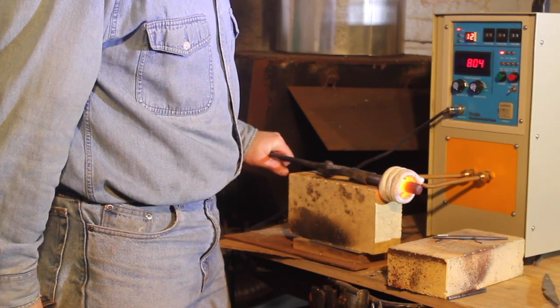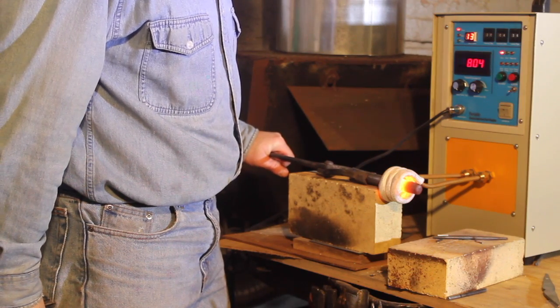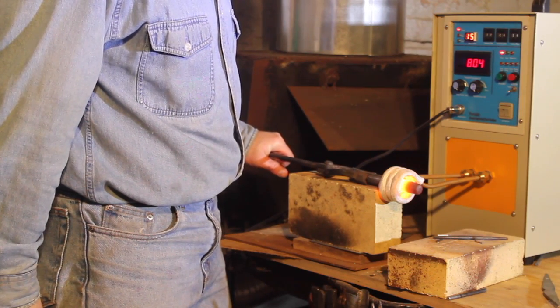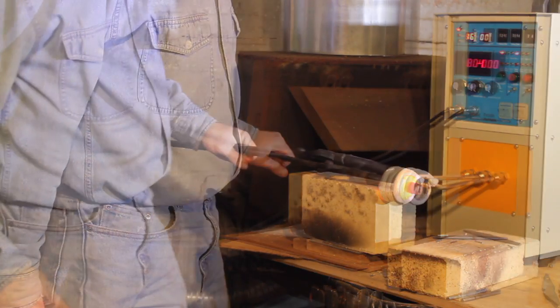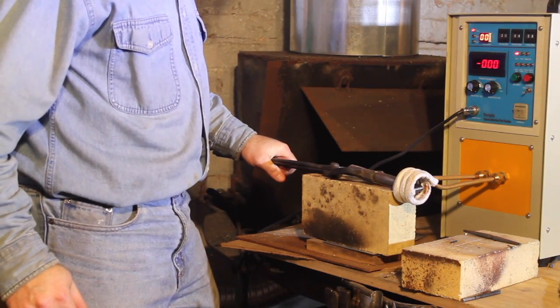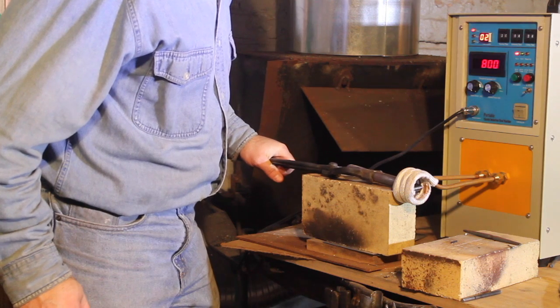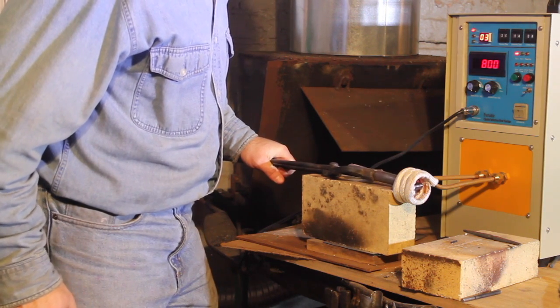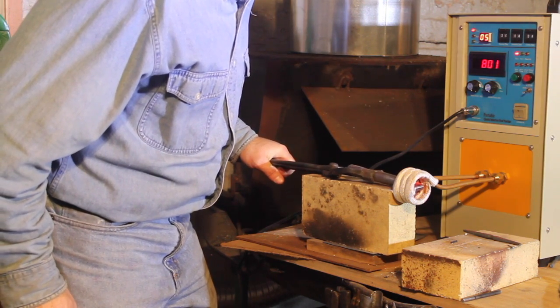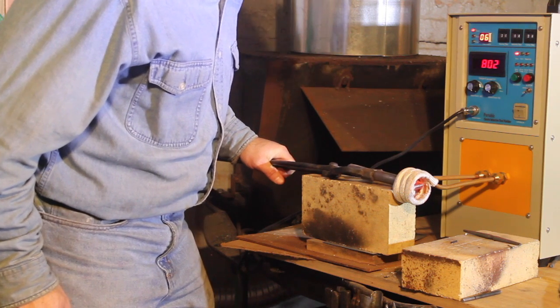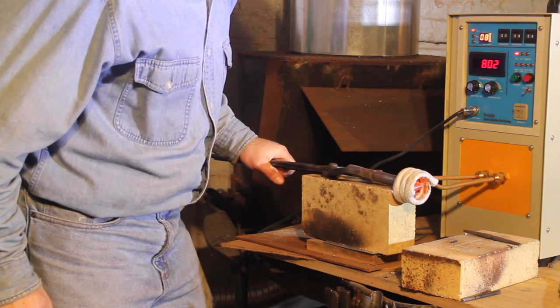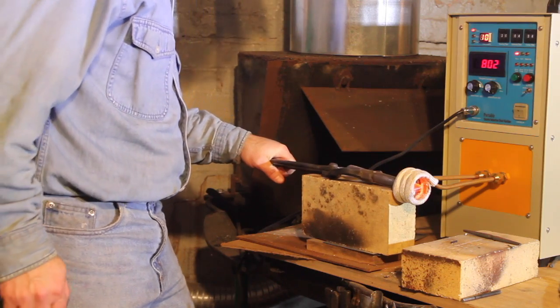Next up is heat treating. Note that with this coil I just can't get a long enough heat for annealing, so I will skip to the hardening. I did rough grinding with 40 grit, then did a successive 120, 220 grit polish, and now I'm ready for heat treating. I'm using full blast heating here, and I'm trying to carefully get it to cherry red.